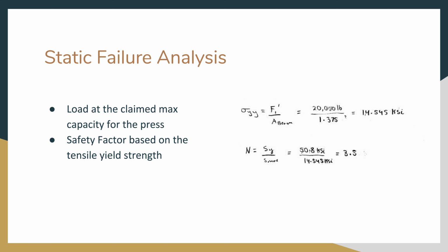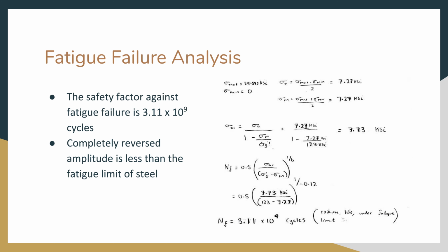Here we have our static failure analysis. So given the load of 20,000 pounds for each vertical support, the axial load was found to be 14.5 KSI, resulting in a reasonable safety factor of 3.5. For the fatigue failure analysis of the H-frame, we assumed a constant amplitude loading of 7.27 KSI, corresponding to completely reverse loading of 7.73 KSI using the Basquin relation.